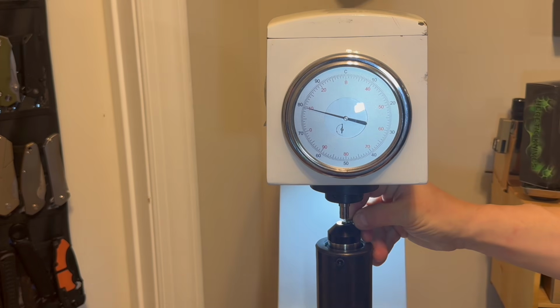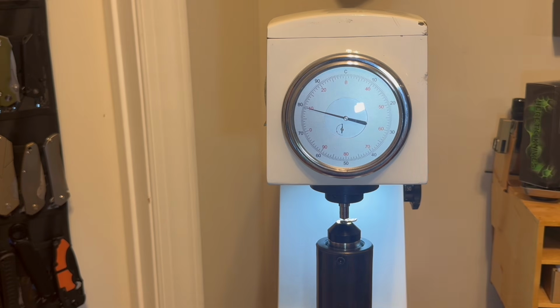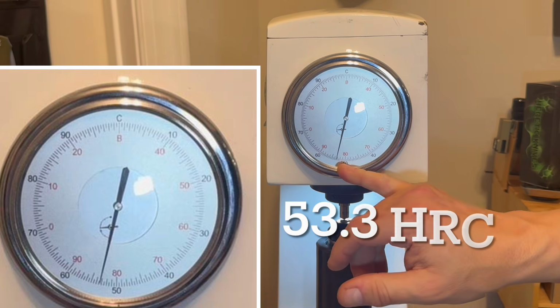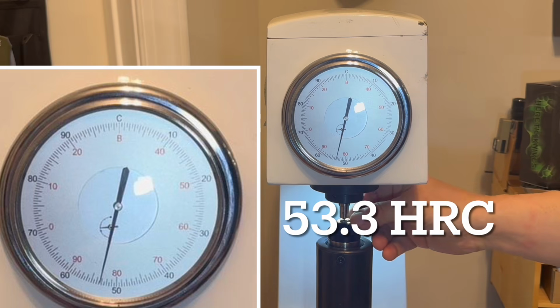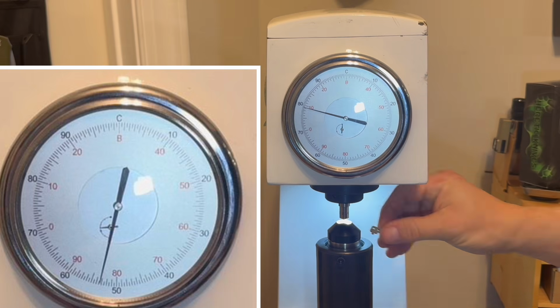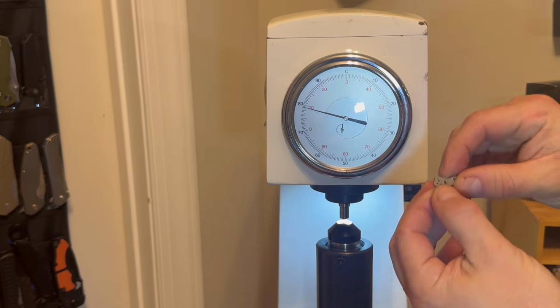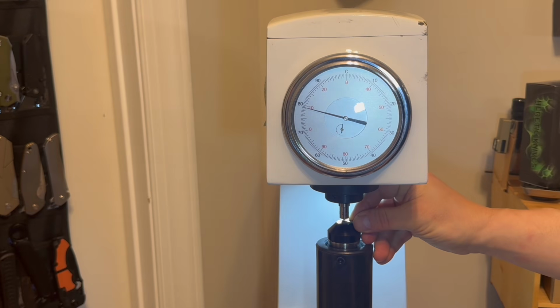Typically, these type of components are made of 410 or 416 cold rolled steel that comes from the mill at about 36 to 40 HRC. Anything above it will be evidence of additional heat treatment that these parts undergo at the factory. And we get 53.3 on the very first poke. That's good news. Let's do another poke just to double check.